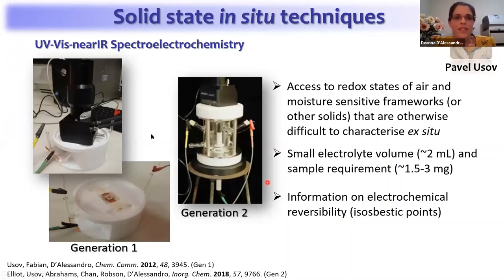So just to give you a little bit of an idea of how we do this, this is an example of one of our first techniques, which is UV-vis near-infrared spectroelectrochemistry. And it's a very, very simple method where we use a three electrode cell. The solid material is placed on the underside of an ITO coated quartz electrode, and we have a handheld spectrometer that simply images the surface of the working electrode as we apply a potential, and we can then measure the spectrum as we change that potential.